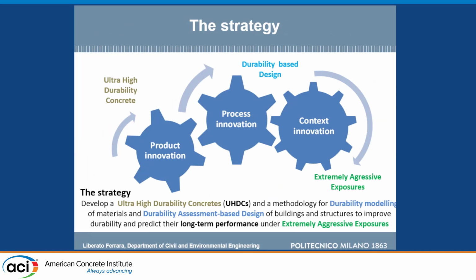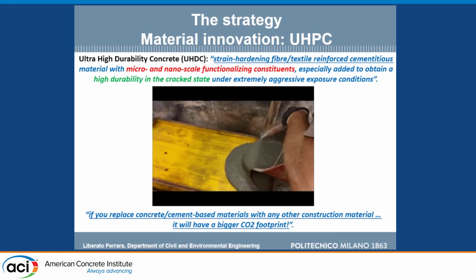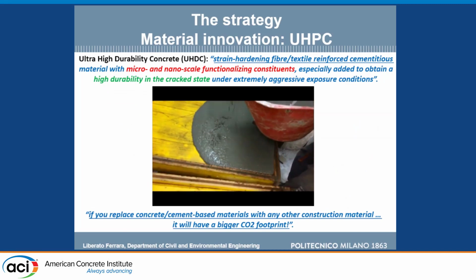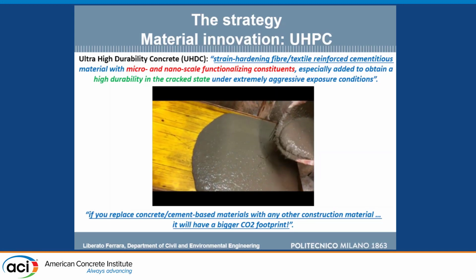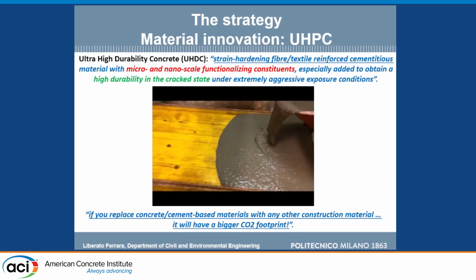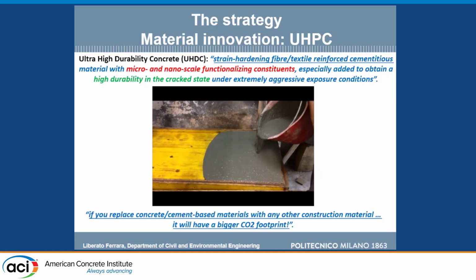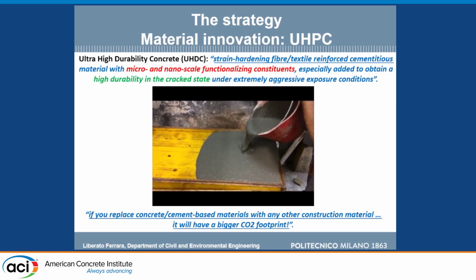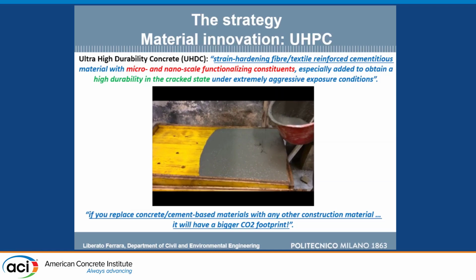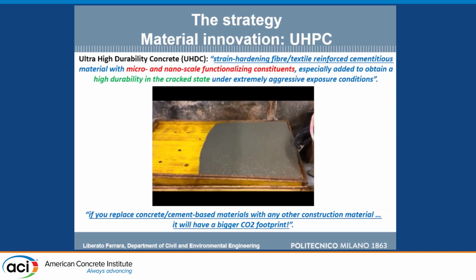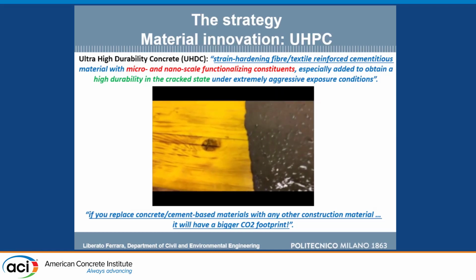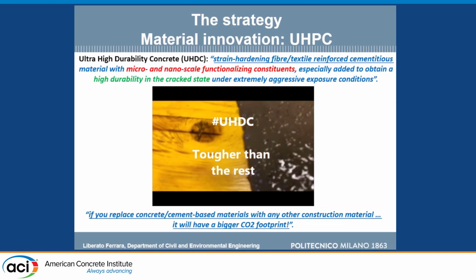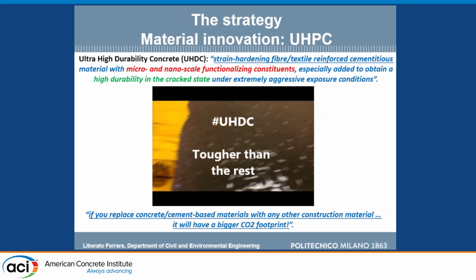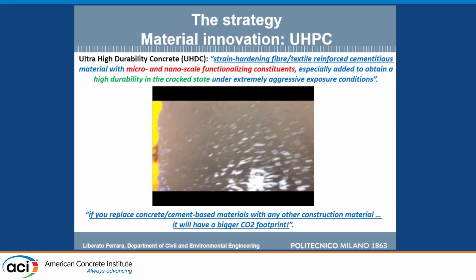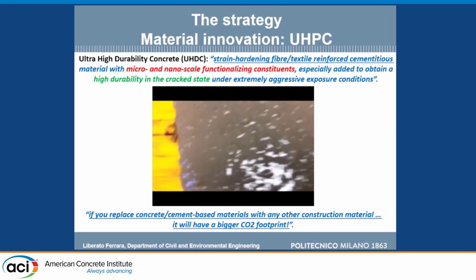We worked at the 3 levels: the product, the process, the context, and started from something which was already in the labs throughout the world: ultra-high-performance concrete. The ultra-high-performance concrete, sometimes you find probably not a complete message to deliver it. You find only a message on very high compressive strength, 150, 180, 200 megapascal, that when you go to structural design, you never use that, because a column cannot be made smaller than a certain size, because it's not a matter of strength, but then it's a matter of buckling. And if you have a beam, the tensile part dominates.